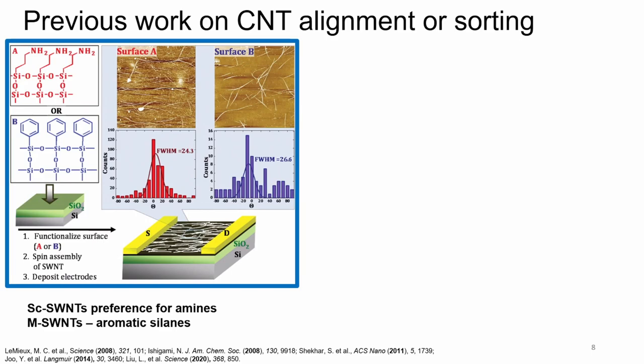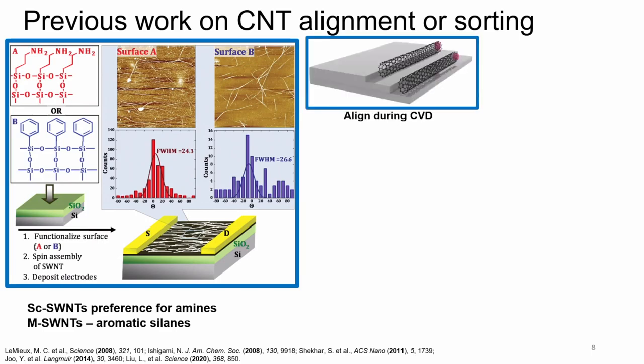So another method of alignment, or to possibly align CNTs, is during the growth process. So how we create the carbon nanotubes. If we grow them on certain surfaces during the CVD, chemical vapor deposition process, a surface such as sapphire that has steps in place for the CNTs to grow, it's possible to have them all aligned. However, in this way, you still get metallic tubes on the surface, so you're not selecting for the different types.